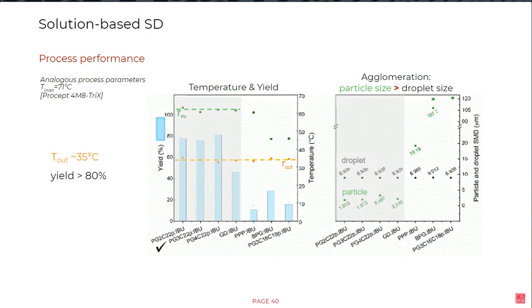So the very first clear conclusion is that at least a difference of 20 degrees should be given between the outlet and, let's call it, the real melting point of the formulation in order to increase the yield and provide less agglomeration. This is clear, and that can also be applied for other kinds of materials such as sugars, considering the glass transition and so on. But for lipids, we can establish that at least 20 degrees should be given.